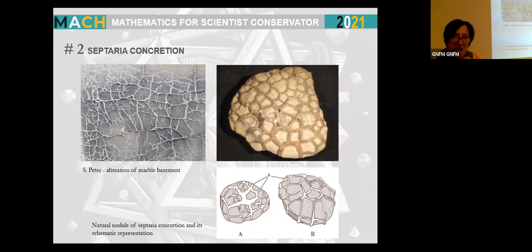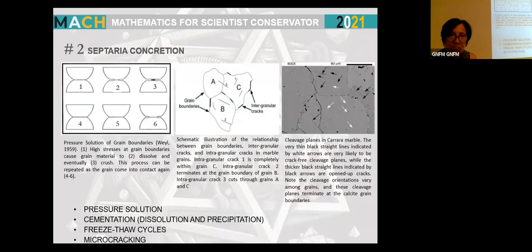The process that creates and characterizes septarian concretion remains unclear to date. Various mechanisms have been proposed, including the degradation of a clay-rich, gel-rich, organic matter core, and shrinkage of the center of the concretion, but all this further evidence shows that cracking involves inner core responses. Pressure solution, cementation with dissolution and precipitation, freeze-thaw cycles, and microcracking are other contributions to the phenomenon's formation.